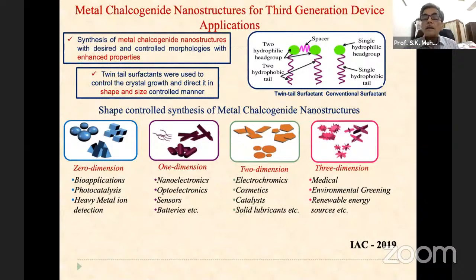Besides that, we have also worked on metal chalcogenide nanostructures for third generation device applications, where metal chalcogenide nanostructures with enhanced properties is the requirement, and here we can use the twin tail surfactants, which are called Gemini surfactants, and we can create controlled shape and size structures. So you can see that we have a spacer in between two head groups, having this tail, two hydrophilic head groups, two hydrophobic tails, and you have a spacer in between. And this is a single one where you don't have spacing.